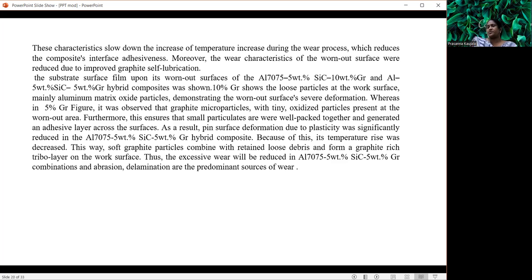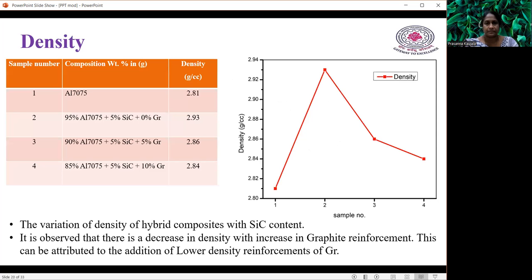So the addition of 5% graphite is giving us the optimized value, because if the lubrication is more, if you are using 10% graphite, it is going to damage the layer. The smoothness will try to damage the layer, which we don't want. So the tribo layer on the worn surface may not be at that optimized value. Thus the excessive wear will be reduced, and abrasion and delamination are the predominant sources of the wear.